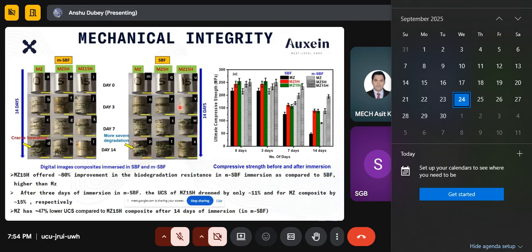We calculated the ultimate compressive strength, and it degraded by up to 11% for the 15 weight percent HA, and for the pure magnesium, it was approximately 15%. You can imagine how the growth factors and the serum are affecting the mechanical strength of the magnesium. If there is already a crack in the implant, then there's a chance that it will degrade immediately. So during manufacturing, we need to keep a lot of things in mind: the machining of any implant and the process we follow should not lead to cracks being initiated in the implant.